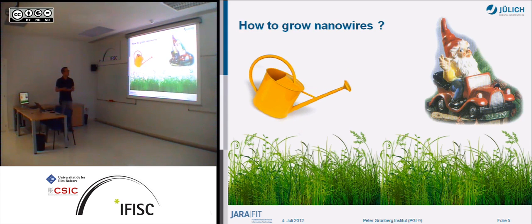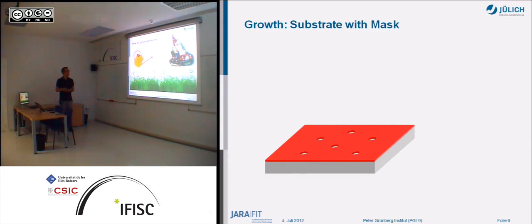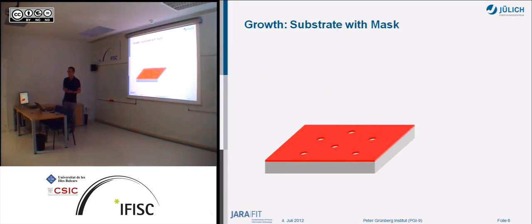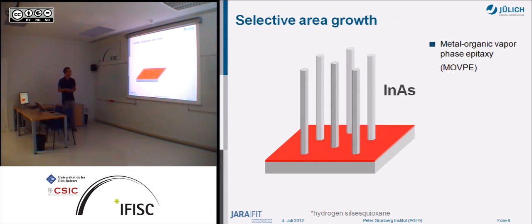Now here is a first introduction to how we grow these nanowires, so how the technology works to grow semiconductor nanowires. It's not like in the garden, but we have a substrate, a ground where the nanowires are grown. We have the semiconductor substrate, which can be gallium arsenide or indium arsenide. This is covered by a thin layer of inorganic resist, HSQ it's called, and by electron beam lithography we prepare some holes here, and in these holes the nanowires grow by metalorganic vapor phase epitaxy, MOVPE.